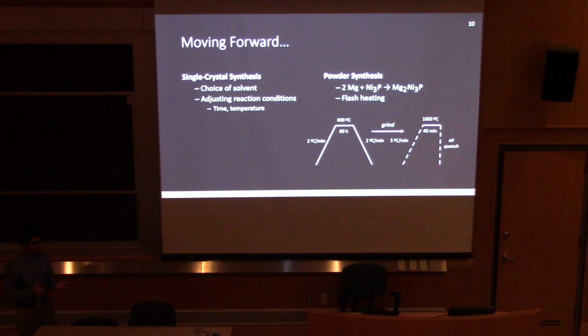Moving forward, we aim to modify our single crystal synthesis by varying the choice of solvent and adjusting the reaction conditions, such as time and temperature. For the powder synthesis, we're trying to have nickel 3-phosphide pre-made, and then add magnesium afterwards, which can alter the reaction and might make it more favorable to form our target compound. Additionally, there's this other method that's been reported in a really old German paper that says we heat it up at this cycle, and then we have another oven that's already preheated to 1000 Celsius. We take it out, we grind it, we then put it in this oven, and then we leave it out to cool in air for a very short time. Maybe it'll work, we don't know yet.